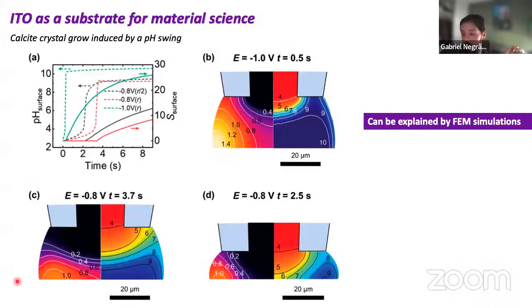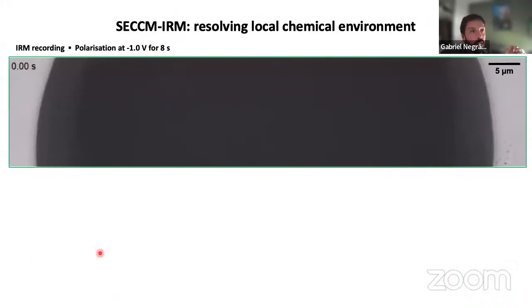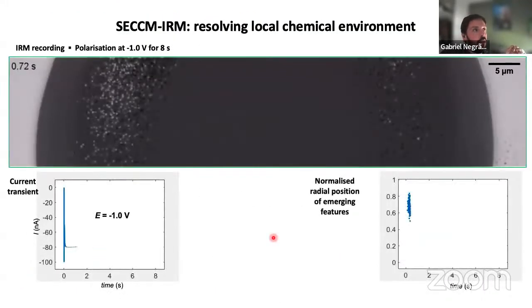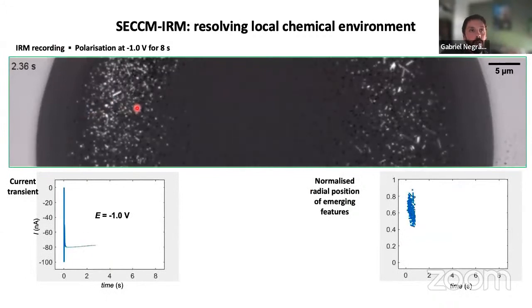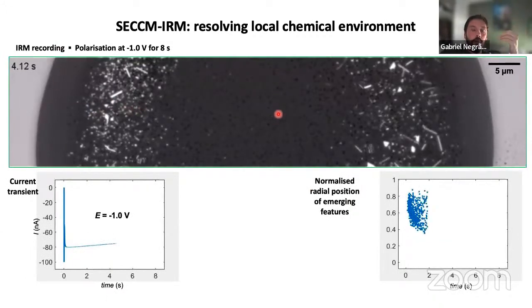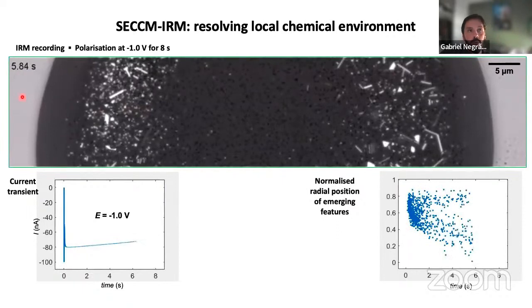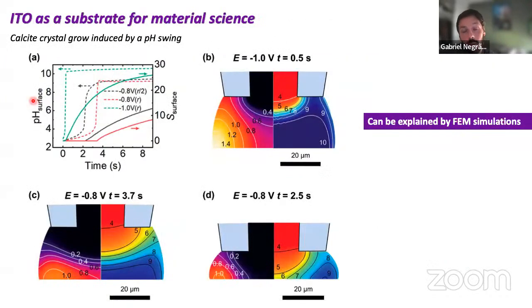And it's exactly the one that we see happening right here in the video, if I can play it again, right? So this is the area that first reaches supersaturation, because of the equilibrium between mass transport from the pipette and mass transport of CO2 from solution. So I think it's quite beautiful that we can not only simulate but also visualize the chemical distribution, and we can use those techniques to probe that in a different way.